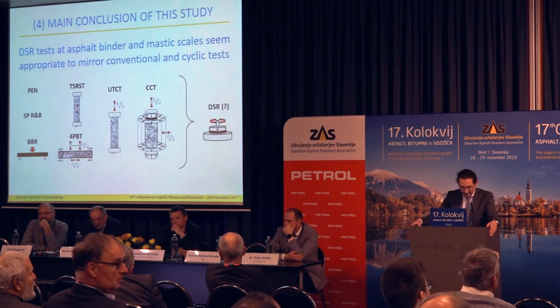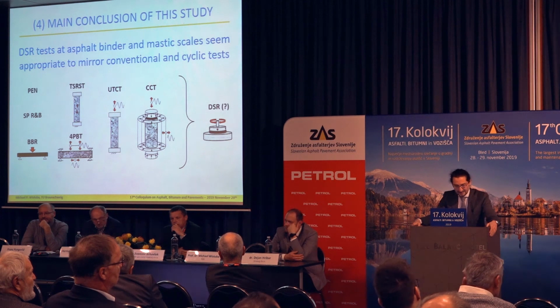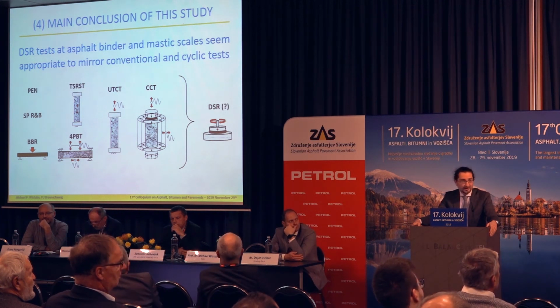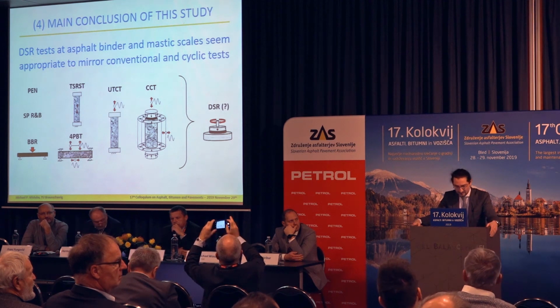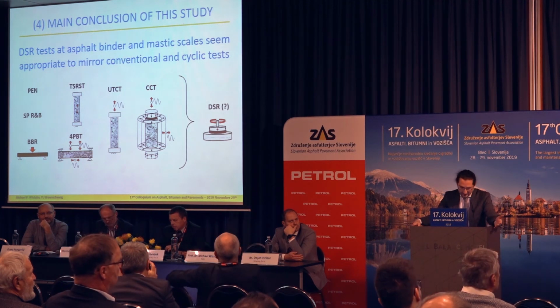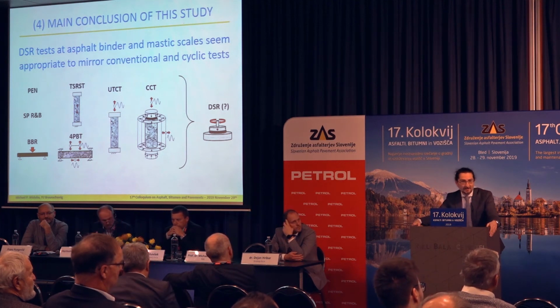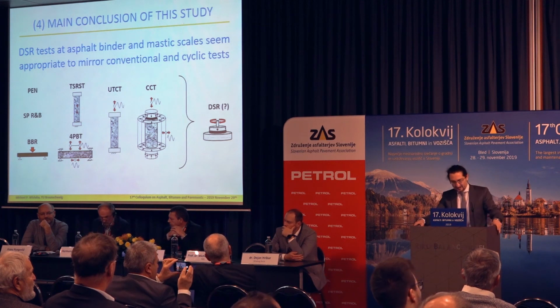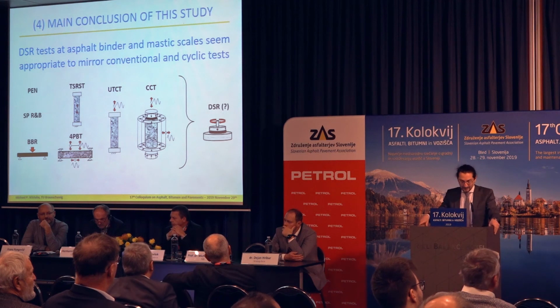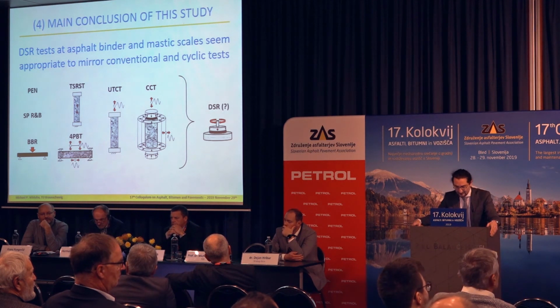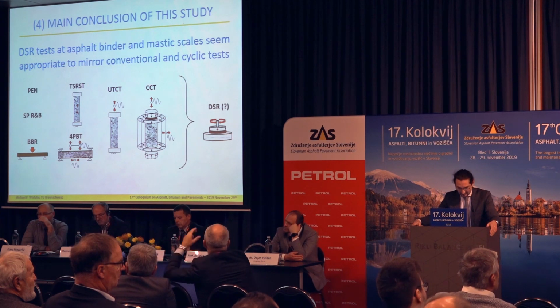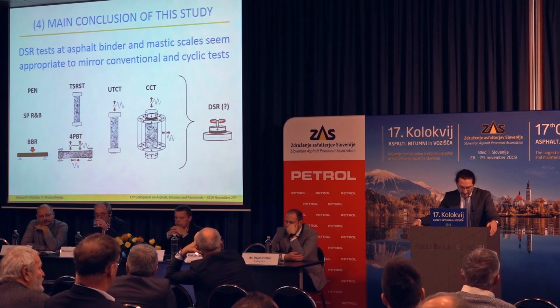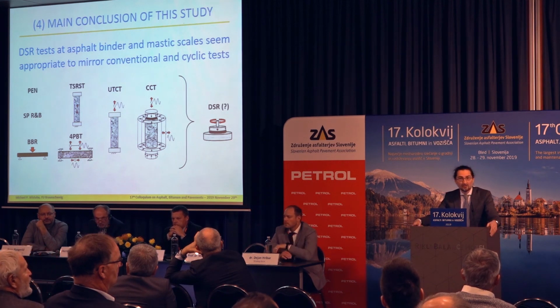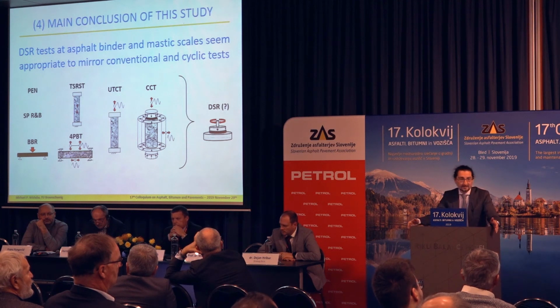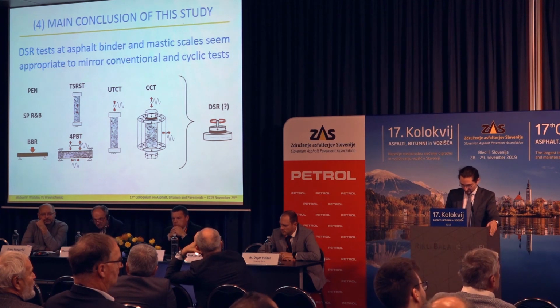So main conclusion of this study is the more and more we see in Braunschweig that DSR testing is a very nice technique, and the results mirror really very nicely conventional tests at the binder scale. So we can replace penetration and ring and ball very nicely with DSR testing at the binder scale. We can also replace BBR tests at the binder and mastic scale by using the DSR. There is a PhD at my institute at the moment which shows this very well, that BBR can be replaced by DSR. And we try to also replace monotonic static TSRST tests and cyclic tests by studying asphalt mastic with the DSR. So that's for today.